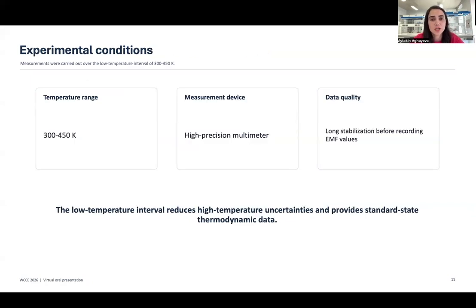The EMF measurements were carried out in the low temperature range from 300 to 450 Kelvin. This temperature interval is important because it is close to standard conditions and helps to reduce uncertainties connected with high temperature measurement. A high precision multimeter was used to measure the EMF values. Before recording each value, the system was allowed to stabilize for a long time. This was done to make sure that the measured EMF values were equilibrium values. Stable EMF values are necessary for accurate thermodynamic calculations.